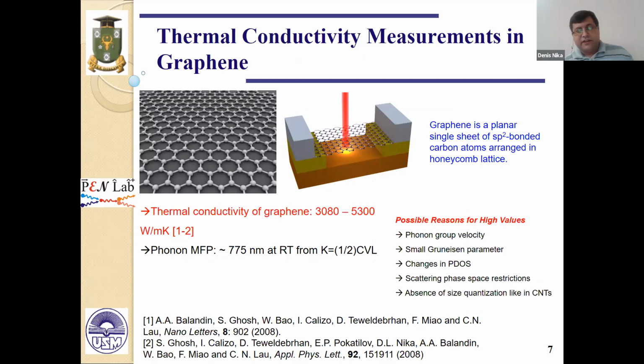Nevertheless, the first measurements of thermal conductivity in graphene, which were done in 2008 in Professor Balandin's group at the University of California, Riverside, demonstrate extremely high values of room temperature thermal conductivity of graphene, between 3000 watt per meter Kelvin and 5000 watt per meter Kelvin. These values are an order of magnitude larger than in bulk copper and 2-3 times larger than in the best bulk heat conductor, diamond, or high quality graphite. Experimental results obtained at the University of California, Riverside have required a theoretical interpretation.